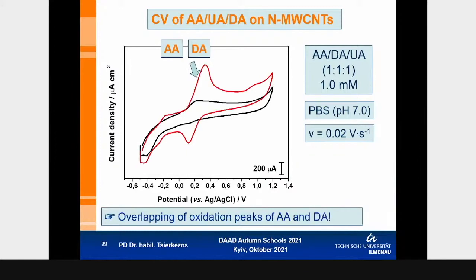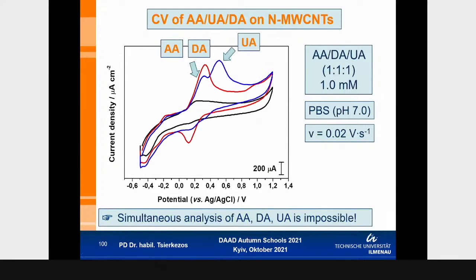And then we add dopamine in the solution, and we observe that the peak of dopamine lies very close to that of ascorbic acid at about 0.3. So the 2 peaks are overlaid. And then when you add uric acid, which lies at about 0.5, you can observe a second peak, which is attributed to oxidation of uric acid. So we cannot clearly see 3 peaks, 1 peak for ascorbic acid, 1 peak for dopamine, and 1 peak for uric acid. We see a peak of uric acid and a peak which is attributed to both of these, which means that this system, nitrogen-doped carbon nanotubes, cannot be used for the simultaneous analysis of all of these compounds.